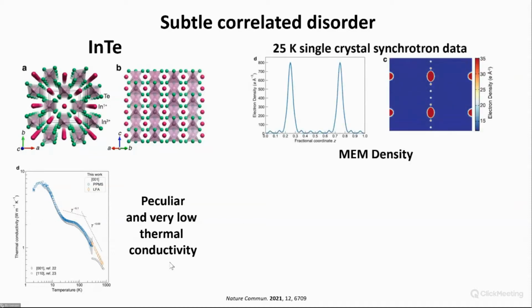And then we go to SPring-8 as usual. We want the best data we can get, at BL02B2, or B1, sorry, and then we measure the Bragg diffraction here on some single crystals. We could see the MEM density and the nice big peaks from the indium 1+ along these chains. But then we also see these secondary maxima. So in between you have these interstitial sites, showing that there is disorder on the indium 1+ position.